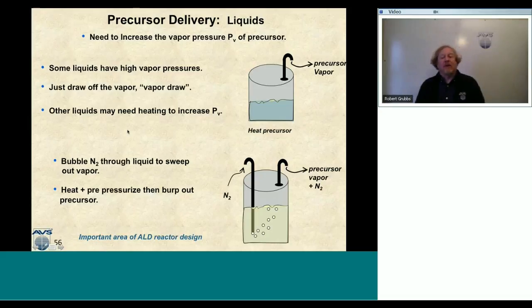The other method is to use a bubbler, and here we'd have a nitrogen straw into the liquid, and I would bubble nitrogen through the liquid, and it would sort of atomize or bring vapor to the surface, and then I can draw that vapor out into my reactor. But these are tricky ways to do it. If you've ever worked with it, you can bump this by accident and get liquid precursor into your chamber, which can cause CVD to occur. So these are tricky. They're doable, but you can do it by sweeping N2 through the liquid, bubbling it up and increasing the vapor pressure that way.